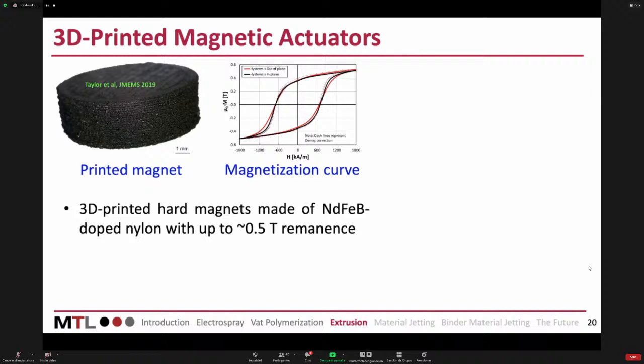So what you see there is a printed magnet that is made of nylon, and it's made of these neodymium particles, and it's a very good hard magnet. You see, it can get the remanence of the order of 0.5 Tesla, which is fairly high. So it's not the highest ever, of course. We cannot put as much microparticles as we would like because otherwise you cannot extrude it. But you can extrude a material that is very decent and very capable as a magnet.